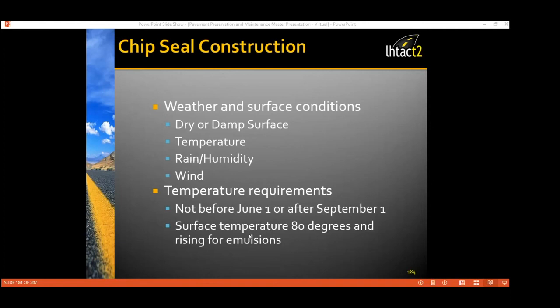As a general rule of thumb for temperature requirements, most will say that we don't want to put this down before June 1st or after September 1st. Many will say we want the surface temperature to be 80 degrees and rising, although I've heard some people say they will start their seal coat operation when the surface temperature is 65 degrees and rising.